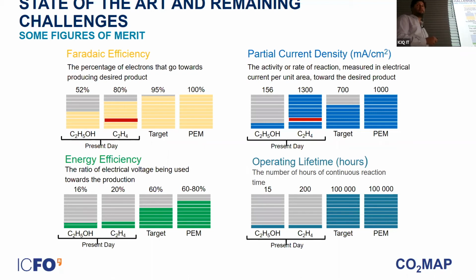And in this red bar, you can see the Faraday efficiency in the case of acidic, so in the case of high carbon efficiency. These yellow lines correspond to the case when we were really bad in carbon dioxide utilization. So when we improved carbon utilization, everything went down. So there is still a lot of room to improve here. There is also a lot of room to improve in the productivity. We have seen today how in alkaline conditions the productivity was very high, even above the required threshold. But when you move to systems that do not suffer from carbonate formation, the productivity that we achieved so far is still far, midway towards the final goal for techno-economic viability.